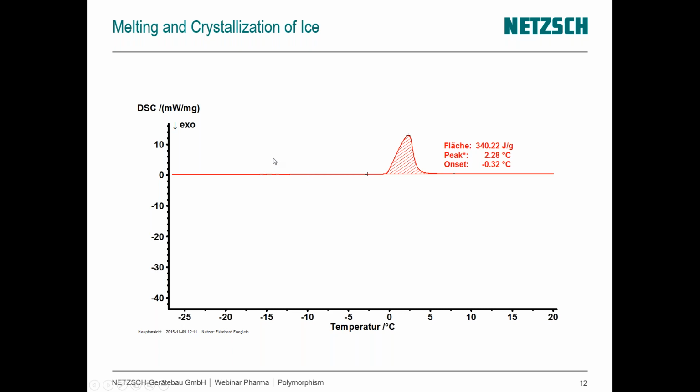If we take ice, very pure, deionized, filtered water, we make sure that we use a very clean crucible. This is an aluminum crucible that's been solvent cleaned, baked. We make sure that the water is extremely pure. And as we go from solid to liquid, of course, everyone understands the melting of ice, very nice and easy conceptual process. We have that onset right near 0 degrees Celsius, and then it's completed.